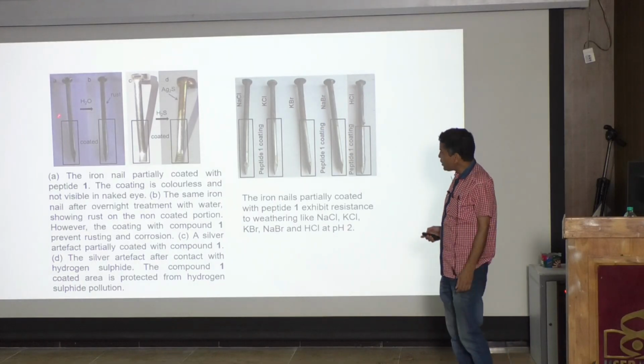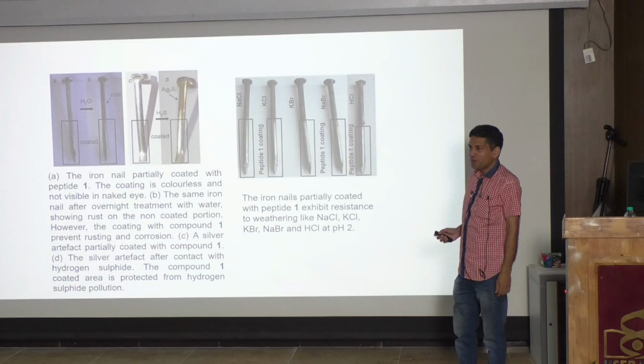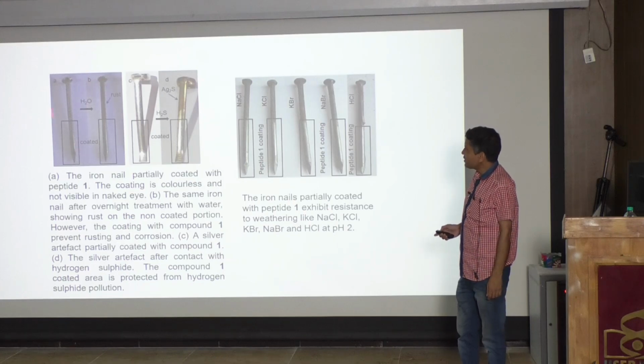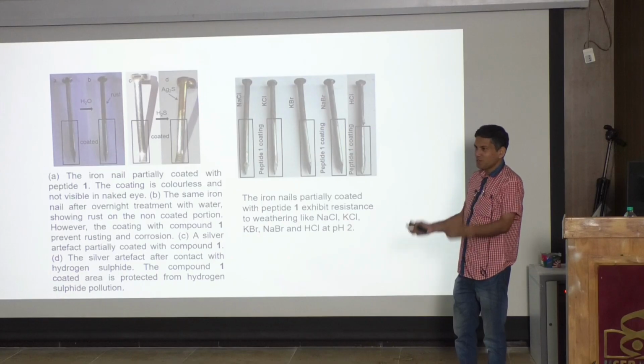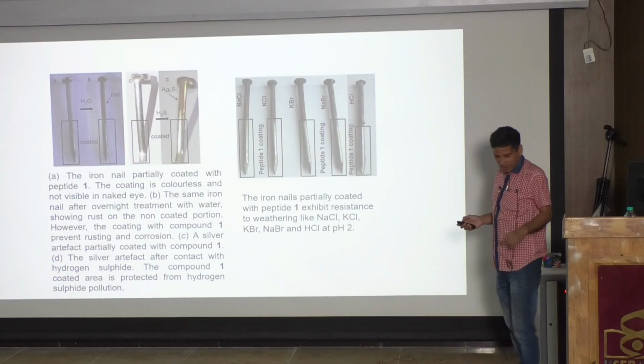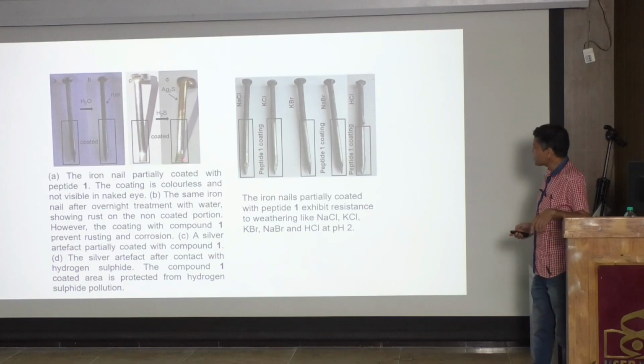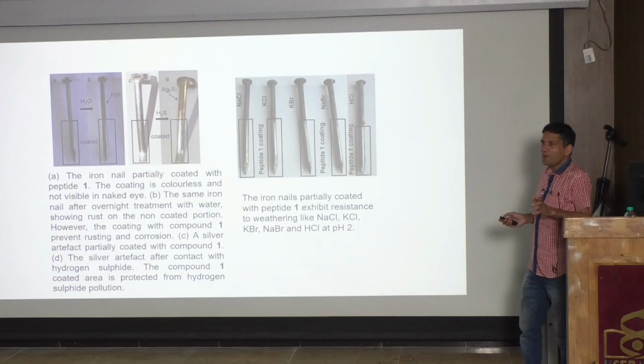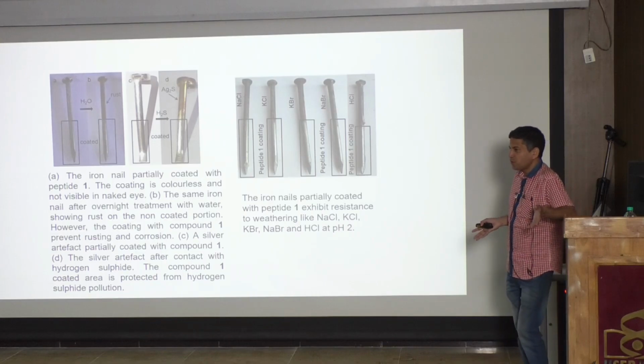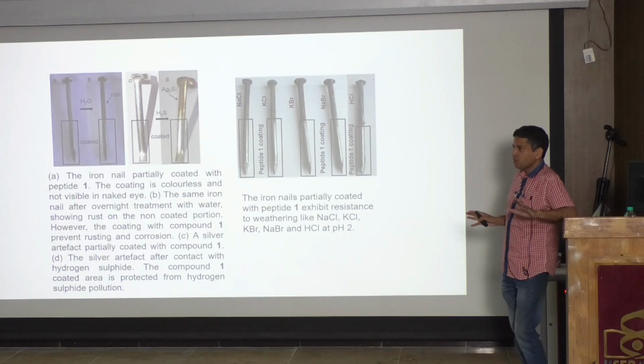Other than that, now these are iron nails. We coated half of the iron nails with our compound, the hybrid material, and put the iron nails inside a chamber containing a lot of water. If it is a common iron nail, overnight there will be rust. But the coated part is intact, while the non-coated part rusts. So now I can challenge that any raw iron, I can protect it from rusting, without any very difficult processing. Just coat with this material. This material is completely colorless. You cannot differentiate between them, and you can protect it from rust formation.